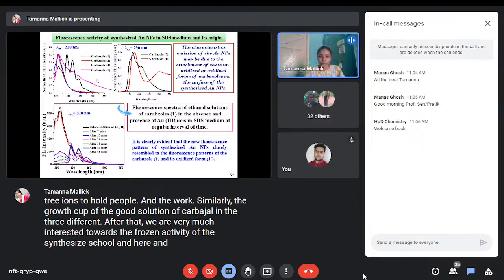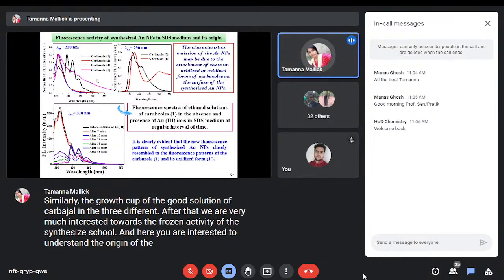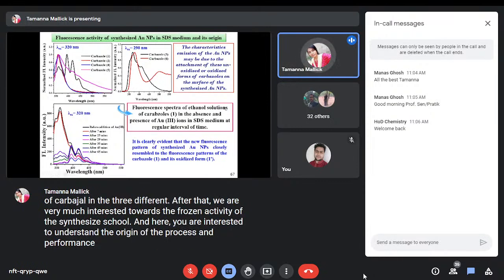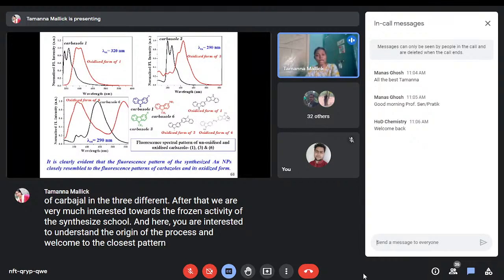And after that, we were interested in understanding the origin of the fluorescence and performed the fluorescence spectra of the ethanol solution of carbazole in the absence and the presence of the Au3 ion in SDS medium at regular time intervals, and it is concluded, as clear evidence, that a new fluorescence pattern of the synthesized gold nanoparticle closely resembles the fluorescence pattern of the carbazole and their oxidized form.